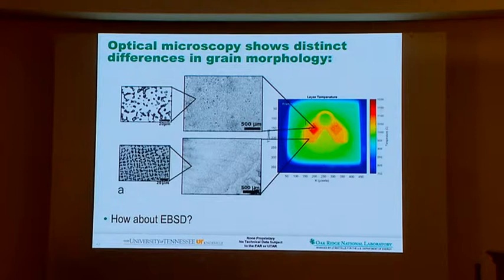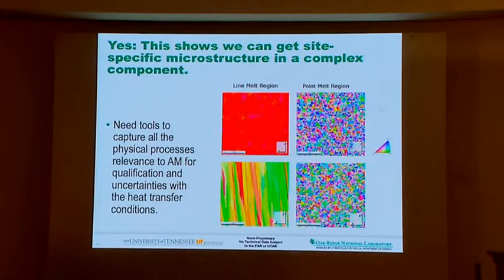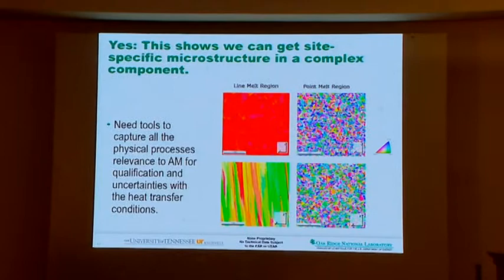Yes, indeed. In those square locations, you can see equiaxed grain structure. Away from that, you get a nice columnar grain structure. Many people don't believe optical microscopes, so we had to do EBSD. We did the electron backscatter diffraction imaging. We confirmed that even in a complicated geometry, you can get these kinds of structures too. So this clearly shows that solidification theories developed by casting are still relevant. You need to understand the heat transfer. So if you're a metallurgist, work with a mechanical engineer who knows the heat transfer, work together to figure out what happens in additive manufacturing too.